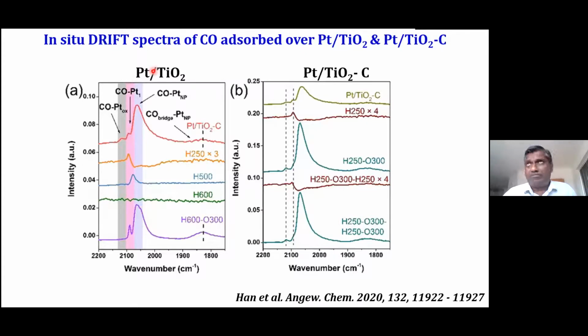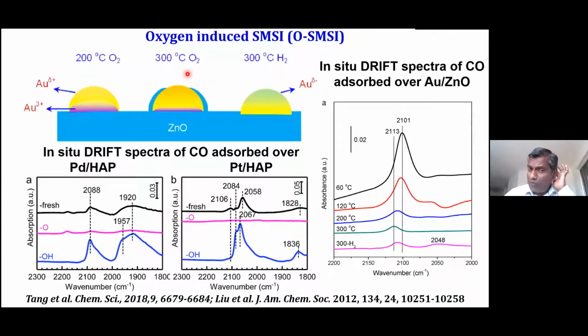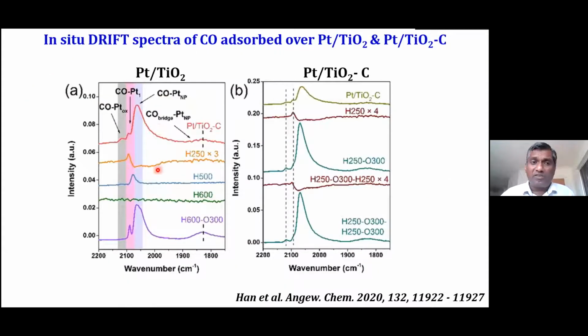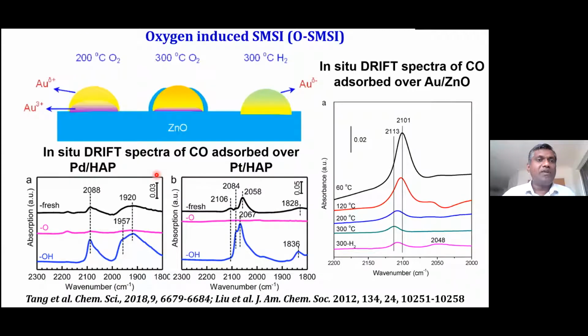And platinum is a platinum group metal that can dissociate hydrogen. Titanium oxide here is a reducible metal oxide. Now, recently, very interesting reports came in the literature. Here, these things happen because of high temperature hydrogenation. One group from Taiwan reported the reverse of this for gold on zinc oxide. For gold on zinc oxide, when you oxidize the sample, the gold surface is covered by a zinc oxide monolayer. This happens when you oxidize the sample.